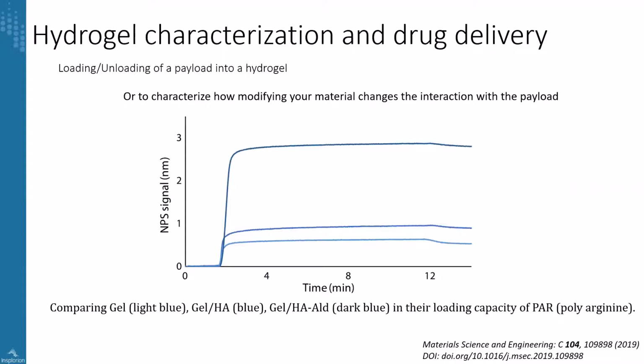In this case, a polyarginine peptide was loaded into 3 different gels that have the same gelatin base, and then 2 of them have been modified either with hyaluronic acid or with aldehyde hyaluronic acid, which change completely the properties. And you can see the difference of the gels, and the gel that contained the aldehyde hyaluronic acid combo shows much higher capability to interact with the polyarginine peptides. So you can easily test how modifications of your material can allow you to increase the payload, speed up the payload, or load more material, unload faster, unload slower. There's a huge amount of possibilities here.